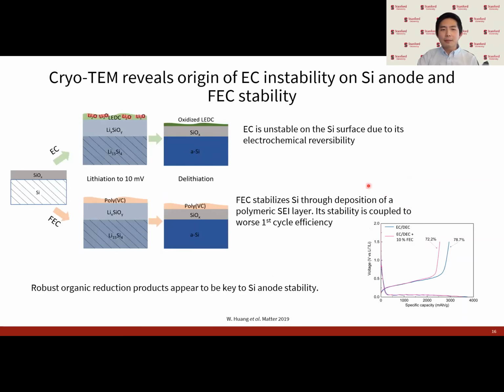And so to briefly recap this work, using cryo-TEM, we can track the evolution of the silicon anode across the entirety of this first cycle. And we can see that the EC reduction product, the LEDC component, is electrochemically unstable on the silicon surface during the delithiation step. But with the addition of the FEC, this poly-VC reduction product is very stable, both electrochemically and mechanically, and remains protective of the silicon surface. And this likely leads to that worse first cycle efficiency we see with FEC, but it also stabilizes silicon and extends its cycle life.